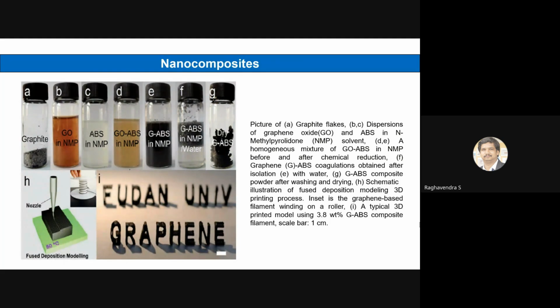Similar to the FDM process itself, here also it is followed. You can see in the bottom left diagram that an 80-degree build temperature is used. The only issue here is frequent nozzle clogging. So whatever composite material we are trying to prepare, if the nozzle gets clogged, you have to remove it and clean it. Maybe we have to change to different nozzle sizes, like 0.4, 0.6, 0.8, 1 mm or 1.2 mm. This trial and error needs to be done, and the final output you can see in picture I, a typical 3D printed model using 3.8% graphene with ABS to finally achieve that output.